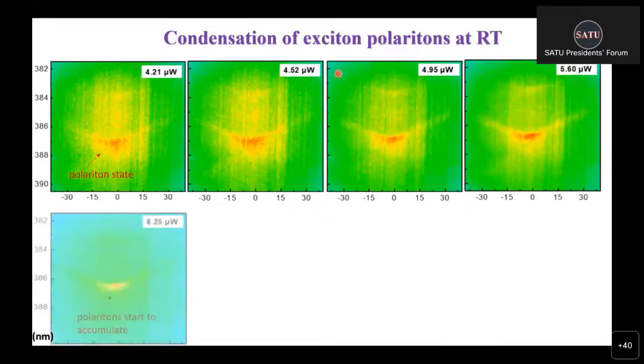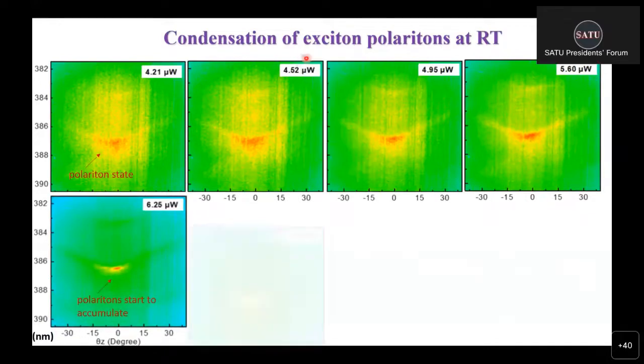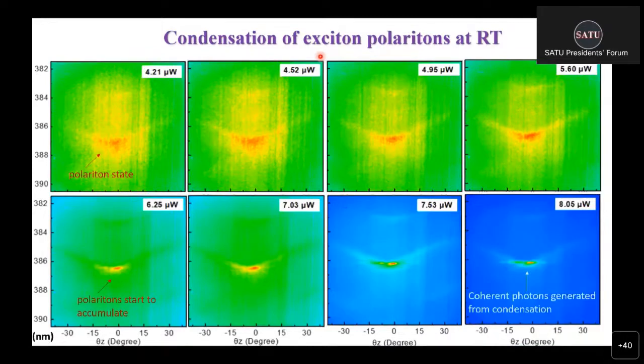The exciton binding energy of zinc oxide is about 60 millielectron volts, which is higher than the thermal fluctuation at room temperature. So we did observe the condensation occurs inside the zinc oxide micro rod when we increase the pumping, and we observe coherent photons generate at the same energy state.